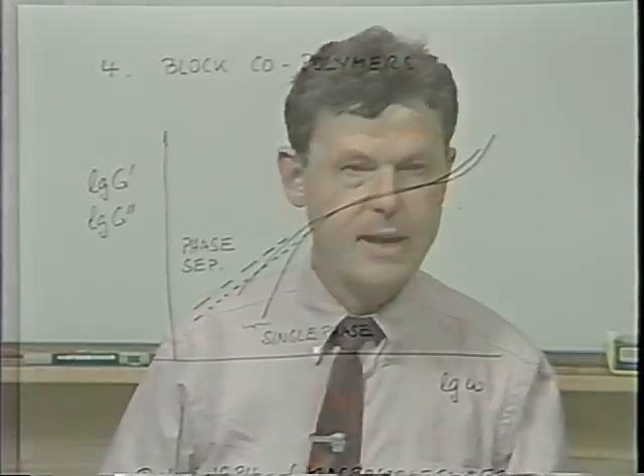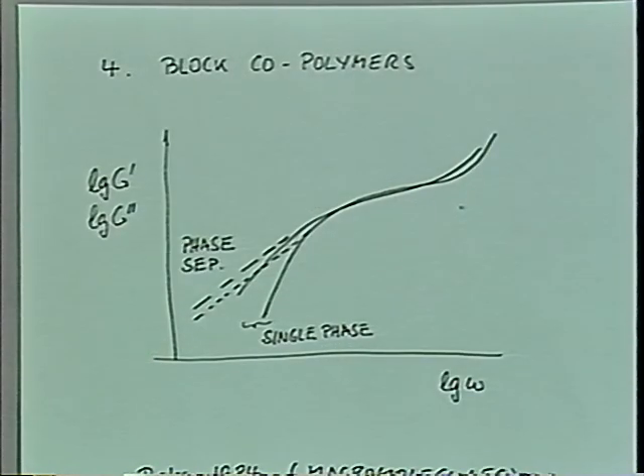There are more examples of power law behavior, and in fact, for those, we might really have a liquid-solid transition. The first example of that type I want to show you is a block copolymer found by Bates in '84. It's actually a di-block material of sufficiently high molecular weight, which undergoes a transition at, I think, close to 90 degrees C. So he had one phase above that and 2 phases below that.